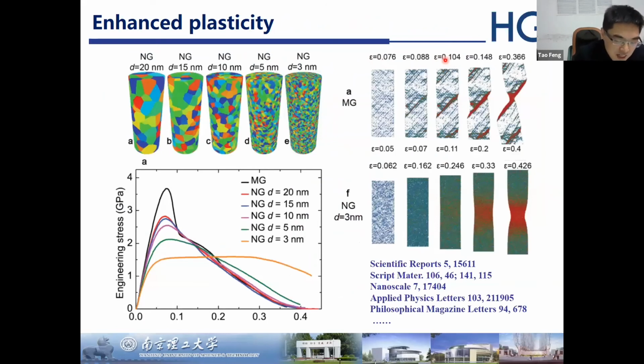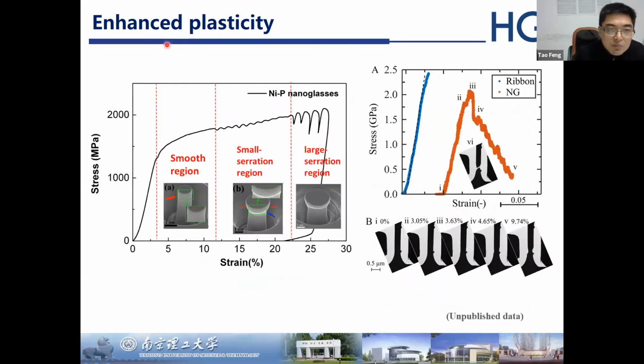And after Professor Gleiter posed this nanoglass concept, there has been a lot of simulation work to demonstrate that the nanoglass would show enhanced plasticity, because the interface can undertake more deformation and form multiple shear bands to retard catastrophic failures. And our experimental results support this simulation work. The nanoglass shows plasticity in both compression and tensile tests, which is a significant improvement in the mechanical properties of metallic glass.